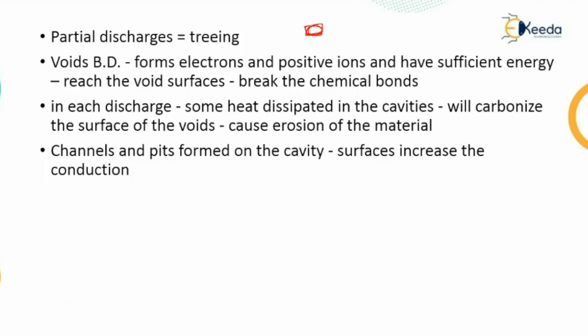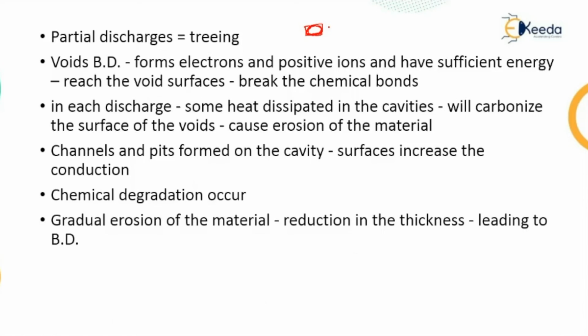These channels and pits that are formed on the cavity surfaces increase the conduction. So it basically reduces the strength of the cavity and hence the overall strength of the solid insulating material, and that can result in an increase in conduction. So this particular surface acts as a conducting path. Now chemical degradation may also occur as a result of the active discharge products that are formed during breakdown. So there is gradual erosion of the material and consequent reduction in the thickness of insulation, leading to breakdown.